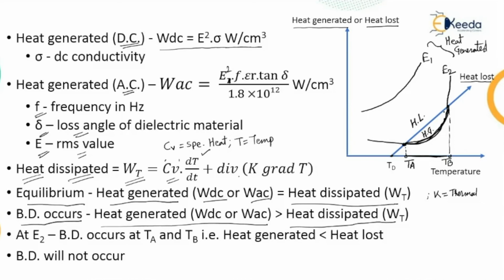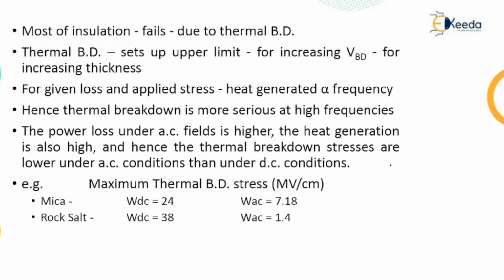But at these two points, TA and TB, the heat lost is less than the heat generated, and therefore there is a chance of getting the breakdown. So this is all about thermal breakdown. A few more points I want to mention: great importance is given by engineers, as most insulation failures in high voltage power apparatus take place due to thermal breakdown. Insulation fails because of the increasing temperature of the insulating medium. Thermal breakdown sets up an upper limit for increasing the breakdown voltage when the thickness of the insulation is increased.